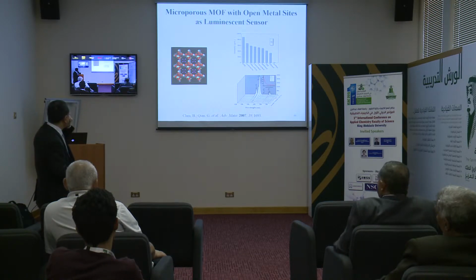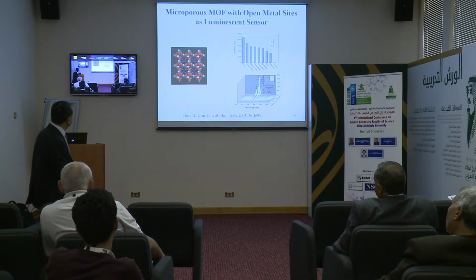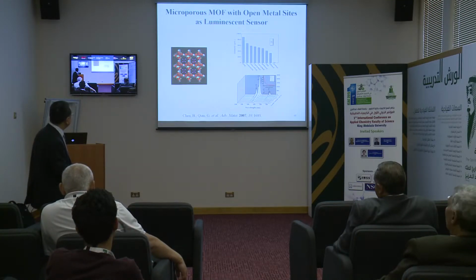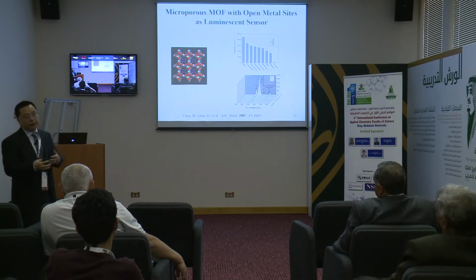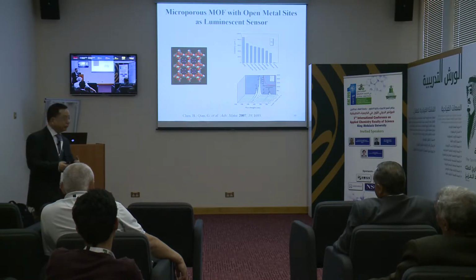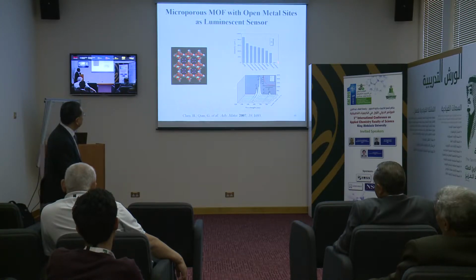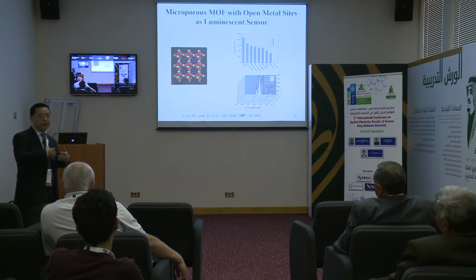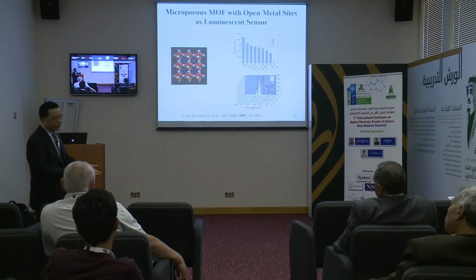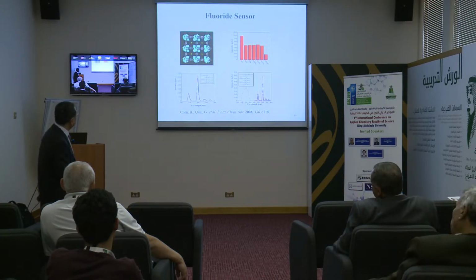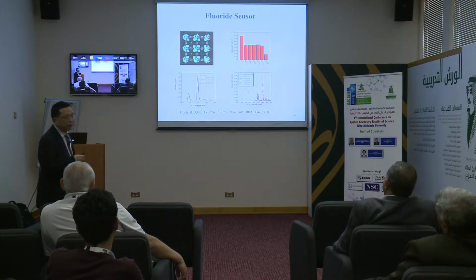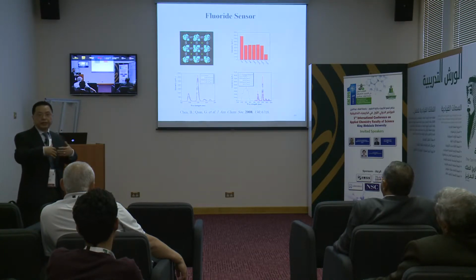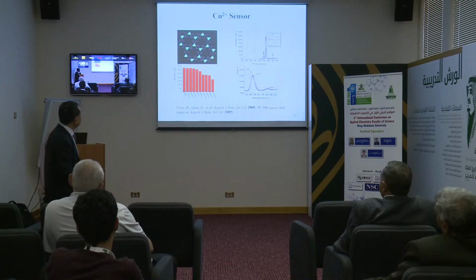We can also use this as a hybrid material, and a luminescent lanthanide can be incorporated. So there is the open metal site, and the luminescence properties are very sensitive to different solvent molecules. The first example indicates that the addition of acetone significantly quenches the luminescence. Once we add a small amount of acetone, the luminescence quenches. So conceptually, this establishes the feasibility as a luminescent center. On the other hand, the fluoride can stabilize the terminal methanol molecule, so it enhances the luminescence properties. These are still conceptual and can also be utilized for cation sensing.